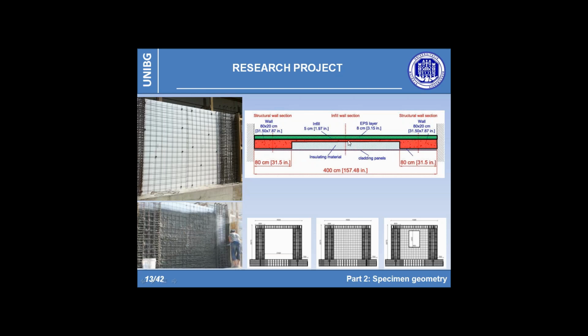So each sample was made of an outer frame having an overall dimension equal to 4 by 2.88 meters, and they are composed of 2 external structural walls of equal size, 80 by 20 centimeters, connected at the top by a beam simulating the top floor slab, and at the bottom to a rigid foundation. The specimen wall 2 and wall 3 differ from the first specimen by the presence of a shotcrete infill panel, having a variable thickness between 2 and 6 centimeters.